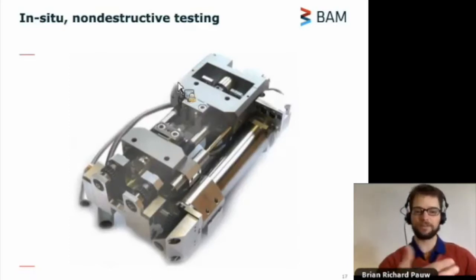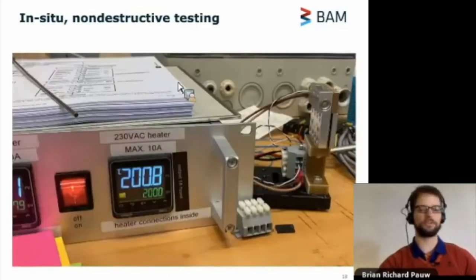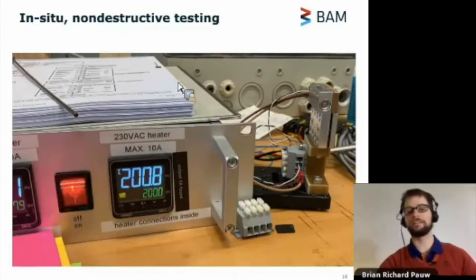We can also heat up your sample. Now, this is a fairly modest heater that we've been building. It goes up to a few hundred degrees. But there are small angle scattering experiments where people have heated up their samples to maybe 1200, 1300 degrees.